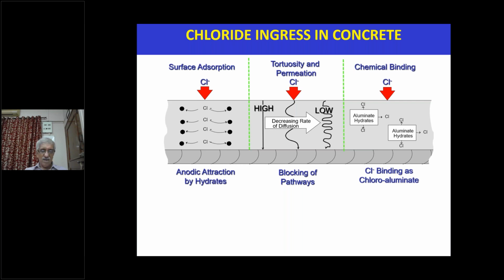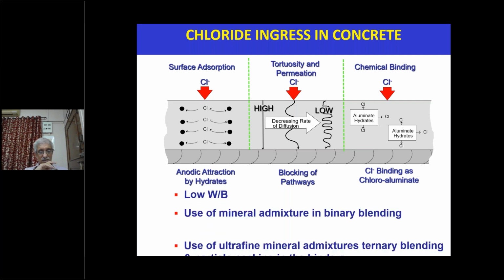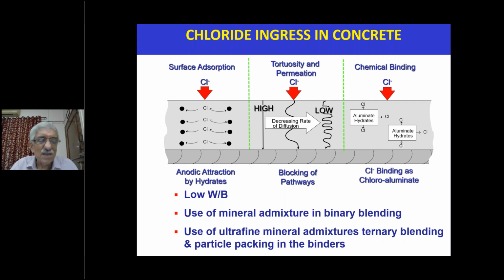Chloride ingress in concrete. This is a very simple way to show how it affects. The first is surface adsorption of chloride. If chloride ingress is there in concrete, some of the chlorides will get adsorbed due to the anodic attraction of the hydrates, and it will take a little longer to reach the steel when there is low water to binder ratio.